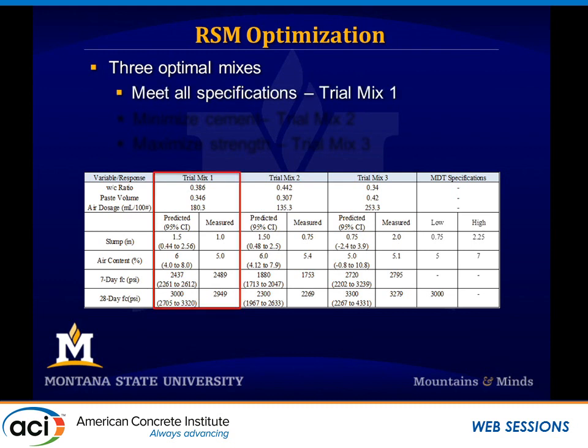So we did one mix, and we said, hey, response surface methodology, give us something that meets all the MDT specifications. Give us something that gives 1.5-inch slump, 6% air content, and 3,000 PSI is kind of what we put on the constraints there. 1.5-inch, 6, and 3,000 PSI. We said, give us that, and it returned to us: use a water cement ratio of 0.386, use a paste content of 0.346, and use an air dosage rate of 180.3 milliliters per pound of cement. So that's the output of our constrained problem here.